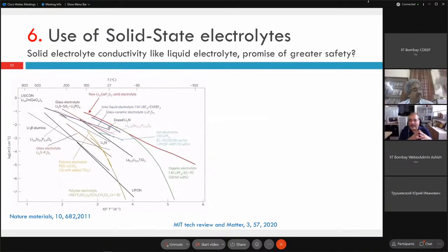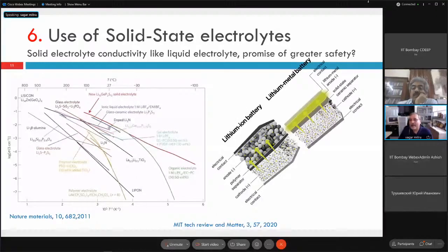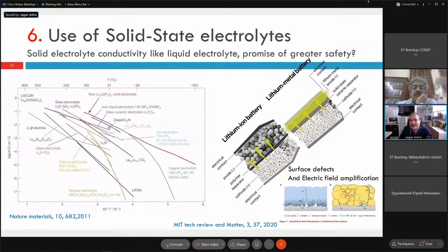Another proposition going on worldwide is the solid state electrolyte as a replacement for the liquid. You can see from some of the graphs that some solid electrolyte compositions work from very sub-zero temperatures to higher temperatures. The conductivity doesn't change much. With the liquid you are currently using, there is no electrolyte conductivity at that lower temperature, which is the reason it is not operating at lower temperatures. So the proposition was that a solid electrolyte in the battery can operate at lower temperature. It works theoretically, but not in the practical sense.